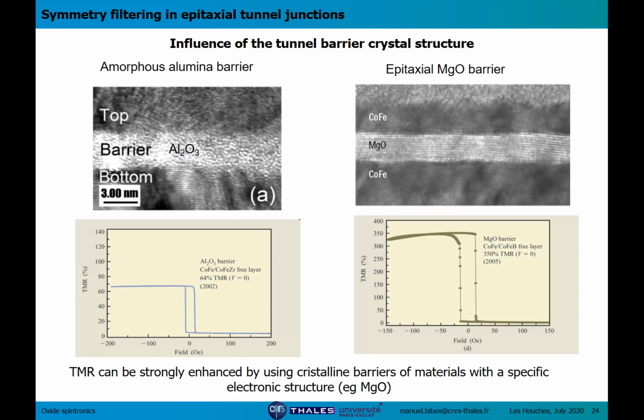Okay, so at the time when we were working with magnetic tunnel junctions, the record values of TMR at room temperature with junctions involving ferromagnetic transition metals like cobalt or cobalt iron, the maximum value was around 50–60%. And there was a very important finding arising from a theoretical prediction that came in 2004 that pointed to the key importance of the nature of the barrier material and also of the crystallinity of the barrier materials.